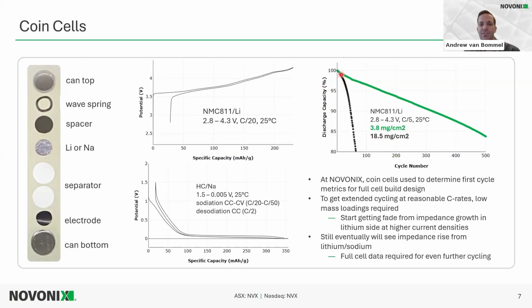And the reason for this is that the lithium impedance builds up with cycling. So we get capacity loss that's just due to the lithium impedance or lithium resistance building up. If we don't want that to happen, we just have to slow down the rate or the current, or you could also just decrease the mass loading.